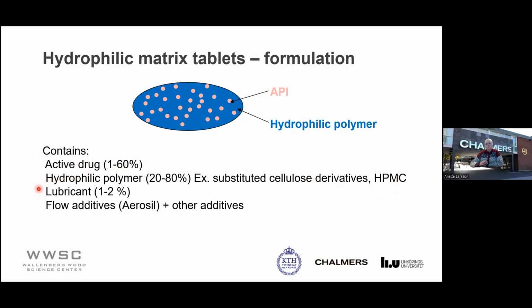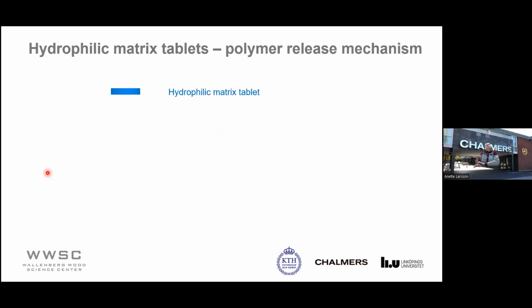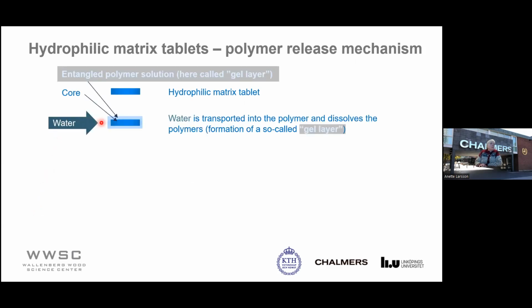But to manufacture them, you sometimes need to add lubricants in the tablet machine, but you can also need flow additives that help the powder to flow into the tablet machine. But we will focus on the two first here, and mainly first on the polymer. So here we have the hydrophilic polymer, and we place it in water. Then the water starts to penetrate and start to dissolve the polymer and create a highly concentrated polymer solution, or what they in the pharmaceutical industry call a gel layer. And the dark blue here is what we call a core. So we have a gel layer and a core here.